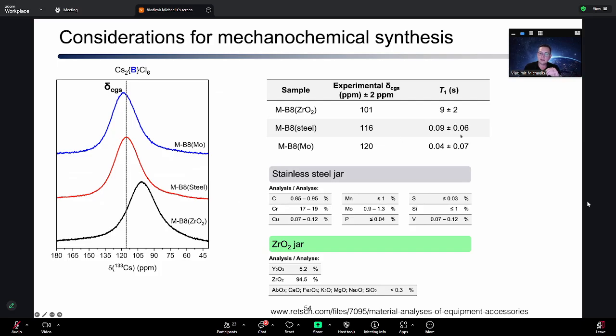I did some T1 data. I'm going to avoid that for today's talk because it's not relevant. But you also have some T1 influences on this. Interestingly enough, your relaxation actually gets very short once you enter your high entropy system. So once you add 5 elements or more, you get very fast relaxation, indicative of a highly entropic material.